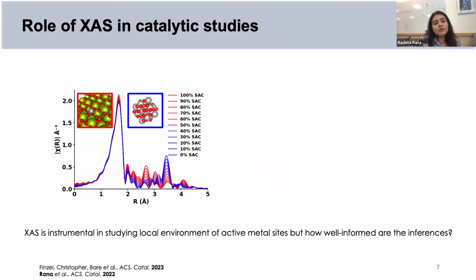And then there was another work that also accounted for these discrepancies or challenges when you have atomically dispersed platinum versus a metal oxide cluster, and how you would differentiate between the two. This was the work done by Phil Christopher's group and Simon Bare's group in collaboration, where they showed that it is sometimes really challenging to differentiate between the two. So just having the absence of that metal-metal bond does not really validate that you have an atomically dispersed site in your material.